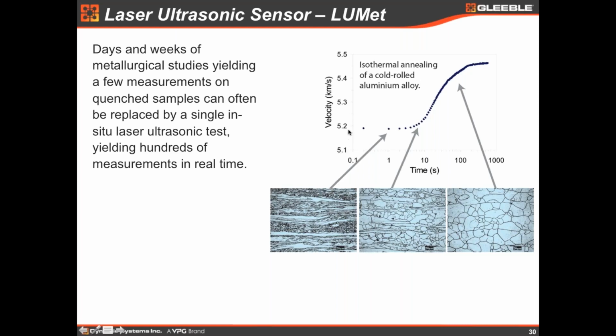So this is a deformed state, there's a low velocity, this is a partially recrystallized state, and then the velocity increases, and at the end of the recrystallization, velocity increases even higher. Of course, it needs some calibration at the beginning, but you can imagine how to see that in real time during a hot deformation test. So this is what saves days or weeks of metallographic studies in the laboratory. So with just one sample, in a few minutes, you can know exactly what's going on in your specimen in real time during the test. So this is the beauty of the LUMet.